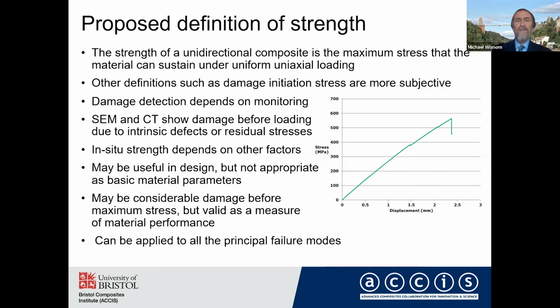For example, damage detection depends on how closely you monitor the specimen. In the graph I just showed a bit earlier, you might very easily miss that point there. And in other tests, if you do very detailed in situ SEM or CT during the test, then you might actually see the damage occurs even earlier.